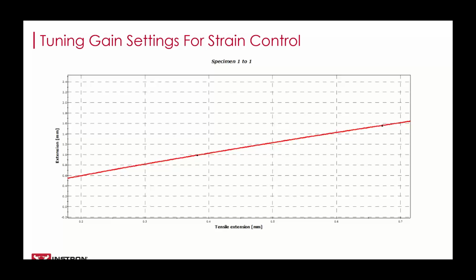The gain setting is used to tell the test frame how much it needs to move the crosshead in order to strain the specimen. When following a typical procedure identifying a gain setting, you'll run a test in the elastic region, comparing the extension of the crosshead against the tensile extension of the specimen. The ideal gain setting will then be the slope of the curve, indicating that you need to move the crosshead Y amount in order to get X extension of the specimen.